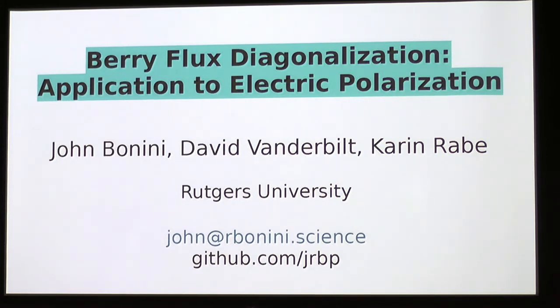That's the reason why we did it. If you try to do it with a slab, you don't succeed. We tried even, but you don't succeed. The surface goes metallic as soon as possible. Now, the quantization of the polarization is something which has to be depurated by those two effects, which I regard as spurious in a sense. And so I insist polarization is a well-defined lattice quantity, and I will show that next, okay?